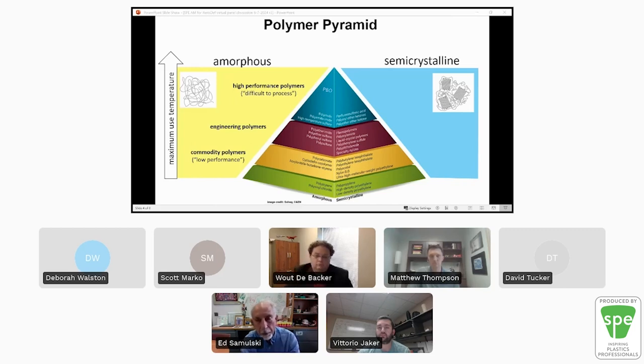You can view the amorphous material essentially as a quenched polymer melt with no structure whatsoever. And at low resolution, the semicrystalline materials can be viewed as crystallites embedded in that amorphous matrix, providing a reinforcement of sorts and physical cross-linking of the material. The properties of polymers in this pyramid increase from the bottom to the top, and along with that increase in, say, maximum use temperature, it basically parallels the glass transition temperature of the polymers.